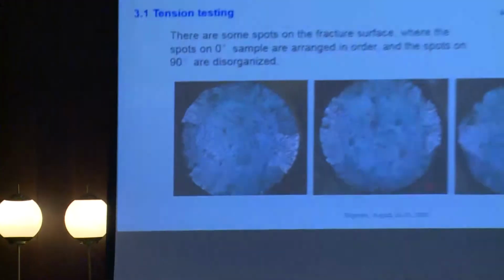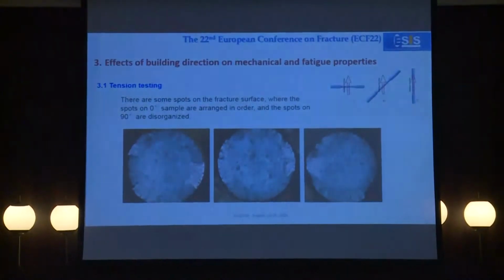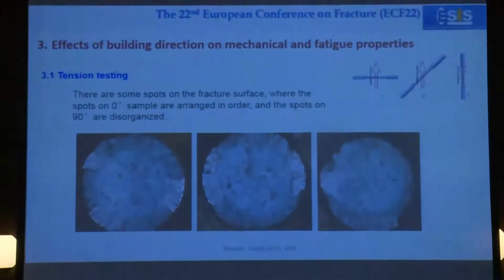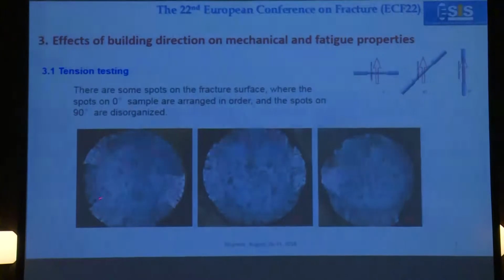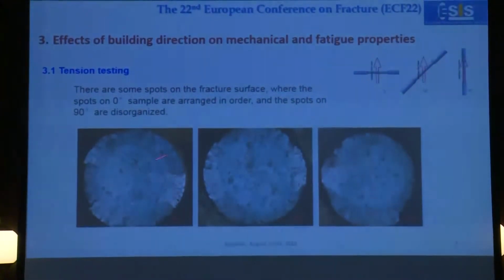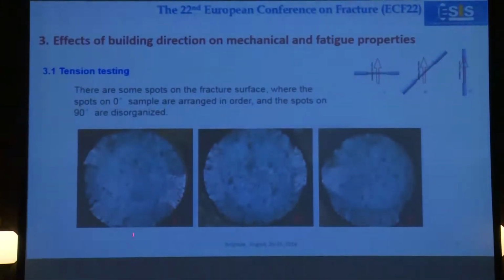This picture shows the fracture surface of tensile samples, and from these pictures we can observe some spots on the fracture surface. For the 0-degree samples, the spots are arranged in order, just like this line and this line. For the 90-degree samples, the spots are disorganized, and for the 45-degree samples, the spots are fewer than the others.